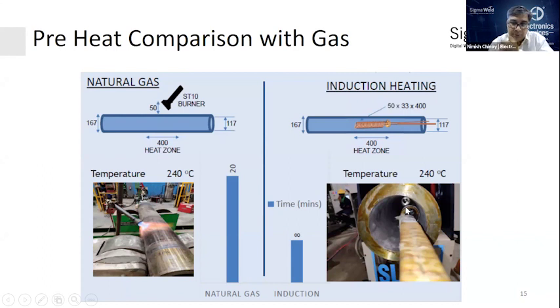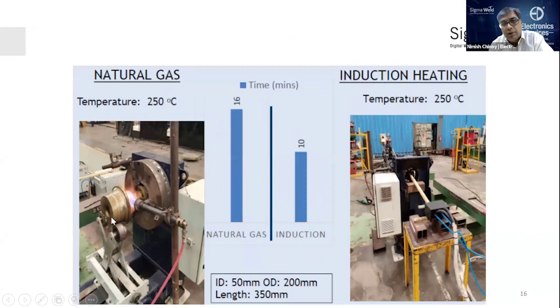Here we were able to heat from the ID, thereby ensuring the temperature when you measure on the surface, the ID is surely at the temperature that you want because the welding is going to happen from the ID. We could achieve the same temperature in under 8 minutes. So you can see there is more than 50% saving in time, definitely also in cost.